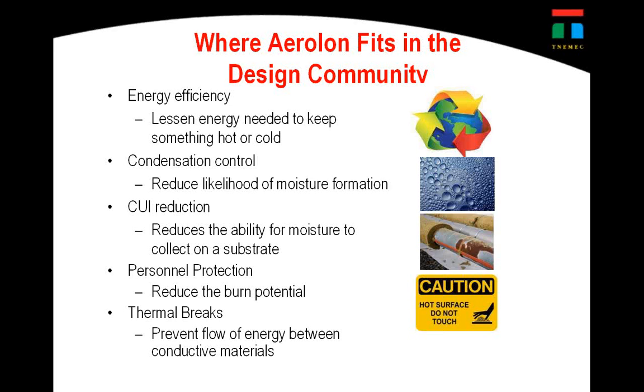Personnel protection. We discovered that we also could put down a thin layer of this material, approximately 1/16 of an inch, and prevent people from getting burned up to 400 degrees F. So that was one of the photos I wanted to show you. And then finally, thermal breaks. We actually realized that what we created was a thermal break.